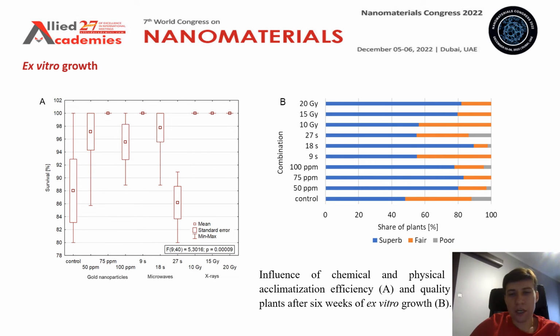And similarly, also the quality of the plants after 6 weeks of glasshouse growth was significantly improved if the plantlets were treated with gold nanoparticles. As you can see, most of the plantlets after acclimatization were of superb quality after the treatment with gold nanoparticles, whereas less than 50% of control plants were of such high quality.